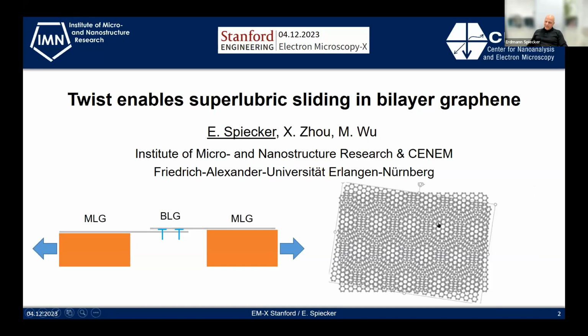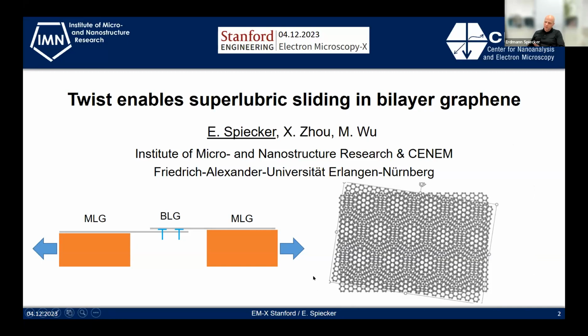twist angle, then you get a kind of moire pattern, and there's a lot of interest in these moire patterns nowadays. If we now slide the two graphene layers on top of each other, we see that the pattern actually remains. The pattern is always the same, only the pattern moves a little bit perpendicular to the sliding direction.